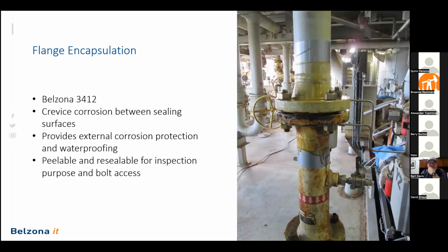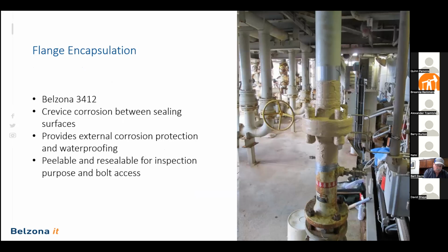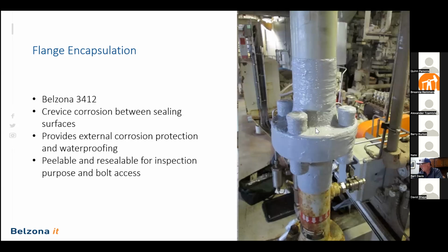And then staying on that industrial side, we see a lot of flanges with crevice corrosion. When it rains, water can get into that gasket area. The bolts can corrode over time as well. We see that a lot, to the point where you can't even open up the bolts or access the bolts. So this is a membrane that you can apply over flanges. It was designed mainly for flanges because it has that application where you create a total flange encapsulation. So you block any water or any moisture from getting into that gasket area. But it can be used in a lot of different scenarios.